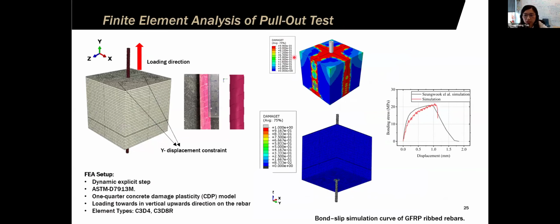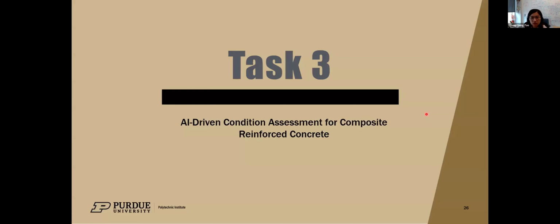And in addition to the fracture test, we also conduct the pull-out test in finite element analysis according to the ASTM standard. We analyze the crack patterns from the pull-out test and compare our results with references. They match quite well in this study. So this simulation focuses on the bonding behavior of rebar and concrete using the dynamic explicit analysis. The modeling results were validated by the experiment from the references and can help us understand the bonding and cracking information between the concrete and the composite rebar.